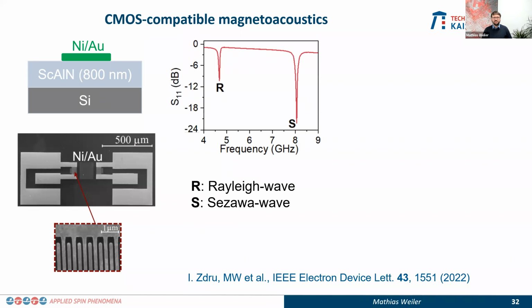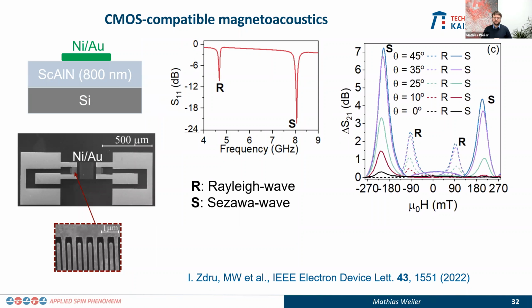And in that system, we also get two types of waves. We get a Rayleigh wave, and the second one here at about 8 gigahertz is a so-called Sezawa wave. That's not really a surface acoustic wave, but a mode that requires an interface between two materials with different mechanical properties, which in this case is the scandium aluminum nitride and the silicon. Okay. And here again, we observe that we can do this magneto-acoustic interaction. It's non-reciprocal, right over here for the Sezawa wave. You see the non-reciprocity also for the Rayleigh wave, a bit less pronounced over here.